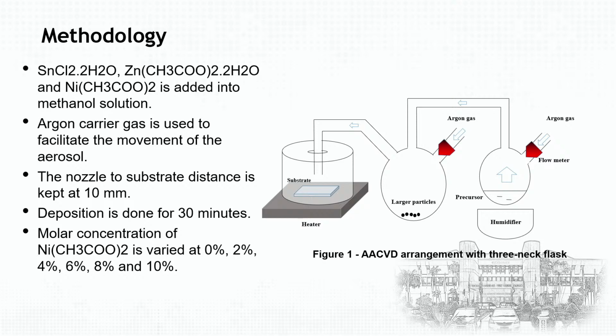Often what has been done, you can see in any shopping mall, even at home, we use aerosol, right? This would be one way to do the experiment. So we use this when we use the heater, and also the substrate, we place the glass on top of the heater, and then we heat it up to 400 degrees Celsius. So this would be one cheaper way to do the experiment.